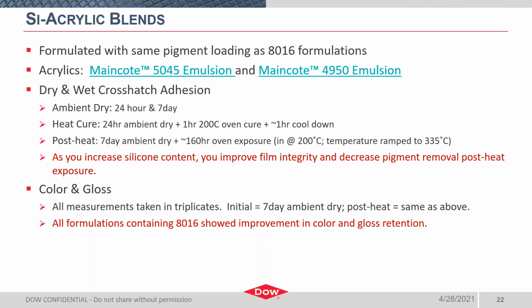For our initial silicone-acrylic study, I chose 2 Dow Maincote acrylic emulsions that find utility in the industrial direct to metal space already, those being the 5045 and 4950 emulsions. I held the formulation consistent for the data that I'll be sharing over the next couple of slides. The optimized pigment to binder and pigment to silica ratios from the high temperature studies were used for all these formulations. Therefore, for the comparison I'm going to show, I only looked at varying silicone to acrylic ratios so I could best understand and quantify the potential synergy between the 8016 and acrylics.